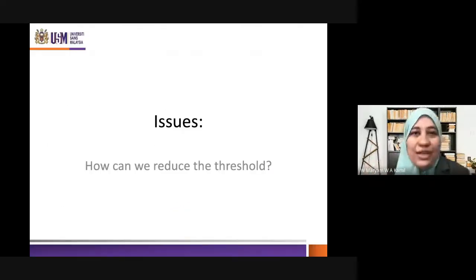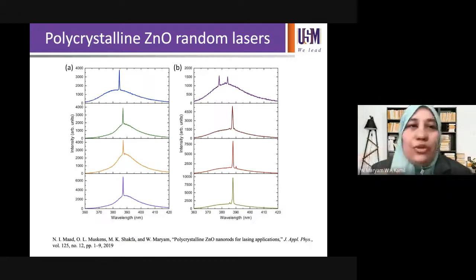It brings us to the second issue. How can we reduce the threshold? Okay, so in order for it to become a beneficial device, the threshold has to go down. Because it relies on scattering, as I mentioned just now, we tried to introduce more grain boundaries. So when we do polycrystalline nanorods, we introduce grain boundaries, and we were hoping that the introduction of grain boundaries will actually reduce the threshold. But no, the threshold went up even further, actually. So it did not work by increasing the grain boundaries. That's what we found out. It wasn't the positive effect that we thought we would have.